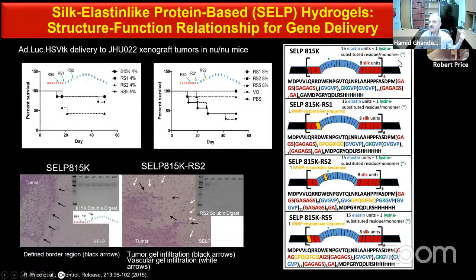If you recall, this 815K is the parent polymer that gave us the highest transfection efficiency. Then we also synthesized a polymer backbone that has, we call it RS1, where the MMP responsive sequence is exactly between the elastin and the silk units. And then we made another type of polymer where the MMP responsive sequence, we called it RS2, is in the middle of the elastin block. And then the third type that we made has this MMP responsive sequence within the silk unit. With traditional polymerization techniques, it's impossible to make such a long polymer of somewhere around 70 kilodalton, where you can precisely control monomer sequence and polymer sequence.